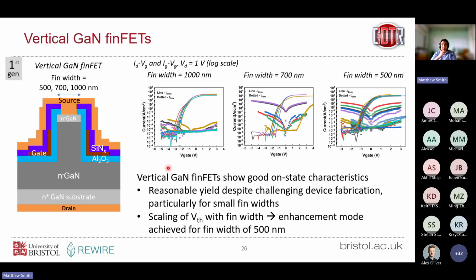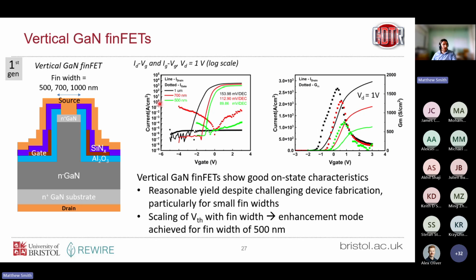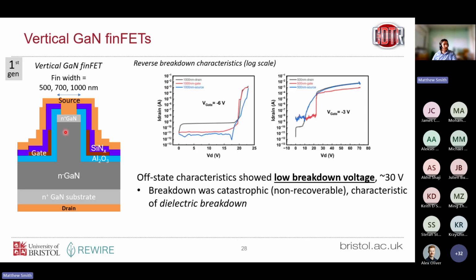So we simulated these devices in Silvaco Atlas, and Victory recently, and we find that everything works reasonably well. All the device properties scale as they should with things like fin width and fin depth. Yes, we can see here 1 micron, 700 nanometers, and 500 nanometer gates, and that threshold voltage becoming more positive as we reduce our fin width, because we've got better gate control, which is really important from a power device perspective. Drawbacks there is we squeeze our fin, so as we make our fin smaller, our current goes down. Again, that's what we expect because we've got less area for our current to flow through.